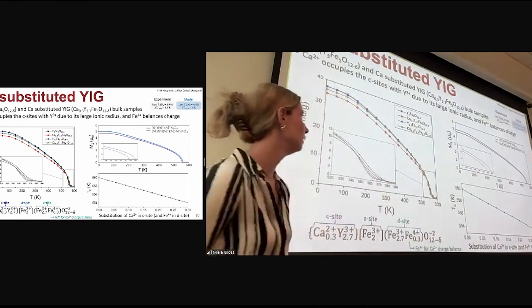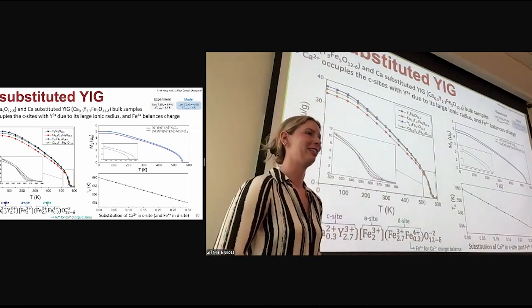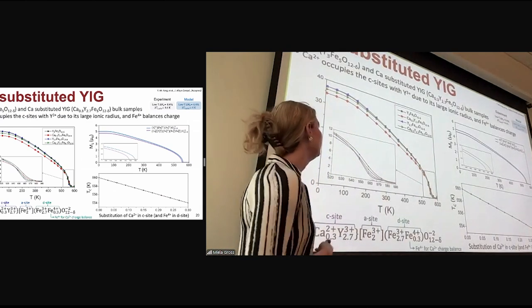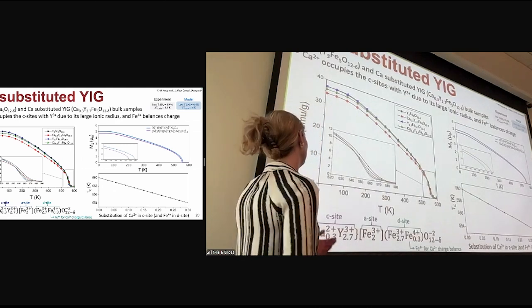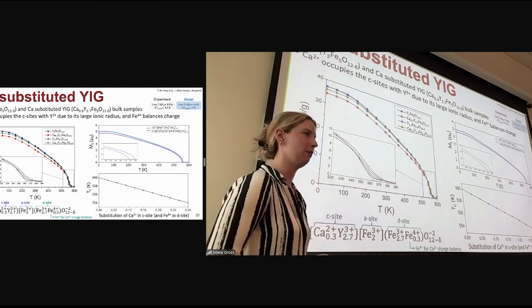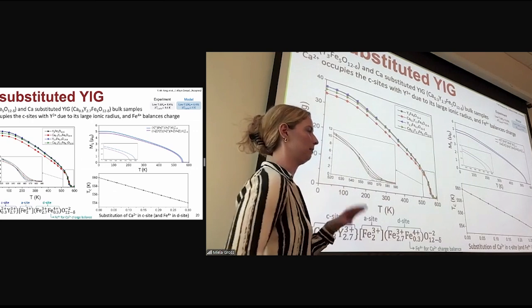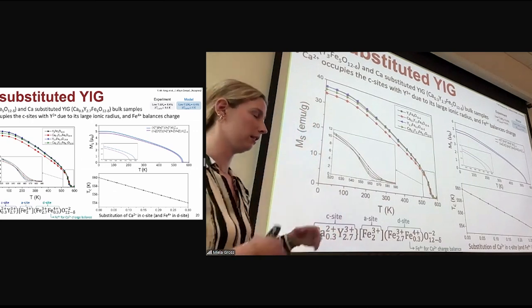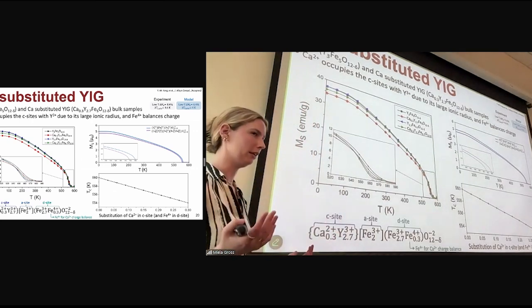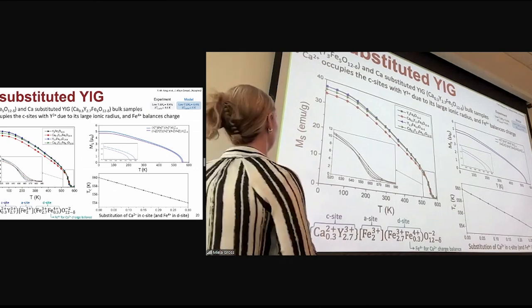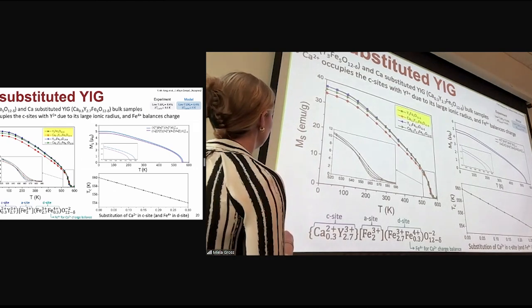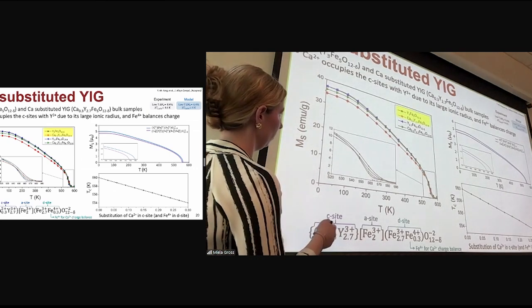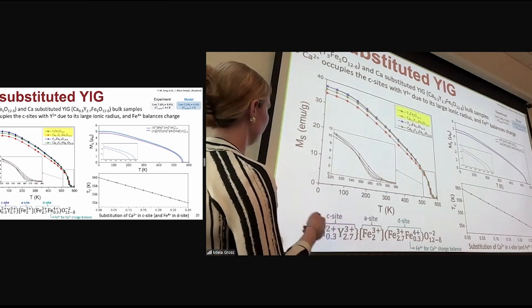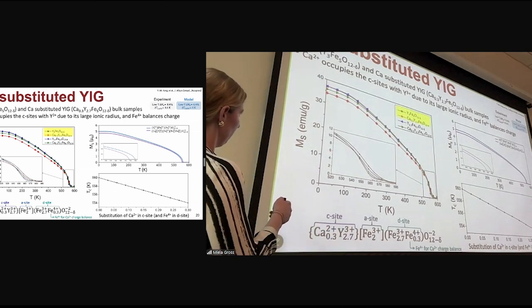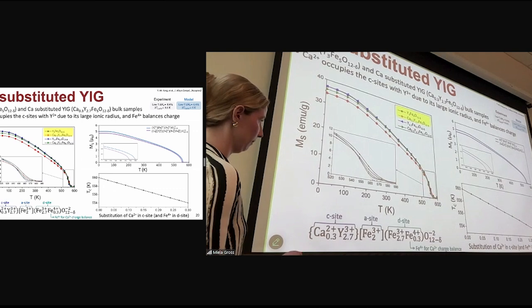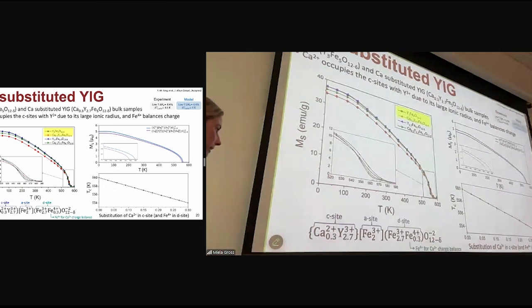In addition, we also looked at calcium substituted YIG of bulk samples. This calcium substituted YIG is really interesting because it's actually a little conductive. But we wanted to understand what was going on with the magnetic moment, because calcium's not magnetic, but nor is yttrium. Calcium would be substituted into the yttrium sites because of its large ionic radius, but why would that change the net magnetization? You can see on these M versus T curves, and I'm going to just highlight the red and black curves up top, that the low temperature MS is a bit lower, and the Curie temperature over here is also a bit decreased.